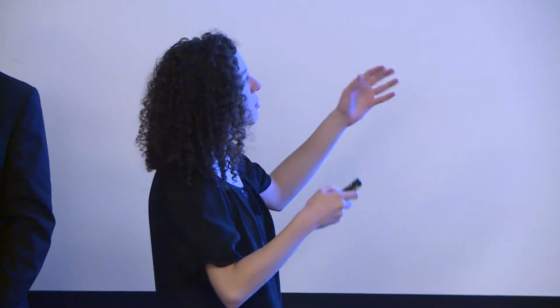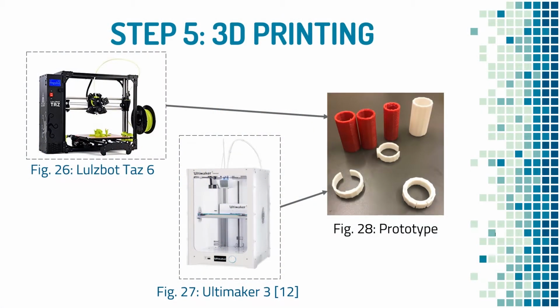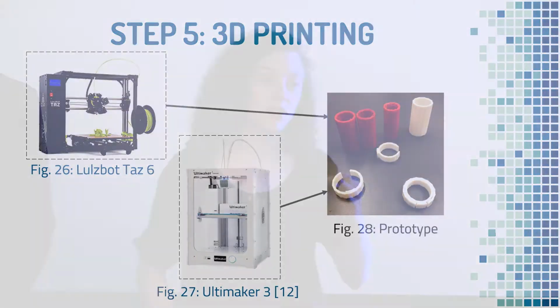Once we have this 3-dimensional design, it's compatible with 3D printing software. The 3D printers that we used were a Lulzbot TAZ 6 printer and an Ultimaker 3. The arrows indicate which aspects were printed. The polyurethane is in red and the PLA is in white. We printed 3 different versions of the polyurethane inner layer: one with the original dimensions, one scaled down by 5%, and one scaled up by 5%. We did this in order to test the tolerances, or how snugly each of those inner layers would fit in the outer layers, which is important when you're relying on a device for its sealing properties.